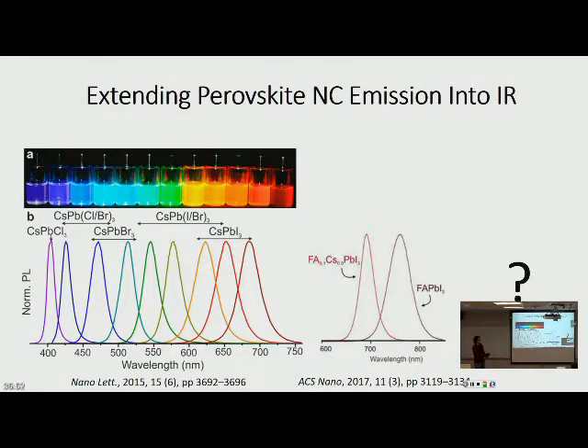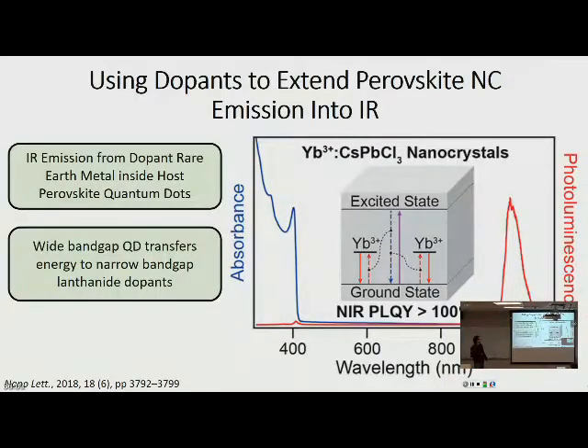So the work we want to do is going further than that. Well, there's supposed to be a little arrow here indicating how far we can go. And just doing some literature search, one way I found that people have tried to extend further into the region is using dopants, or putting dopants into the nanocrystals. They found that if you dope the cesium ones with the wide band gap with rare earth metals, I think they used erbium. They found that they were able to, ytterbium, is that how you pronounce it? I don't know, I've seen the words, but I've never actually had to say it. Ytterbium.